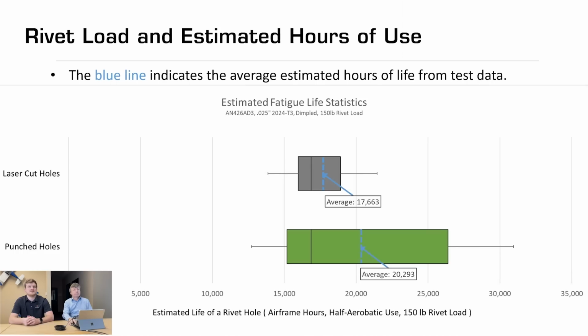So the units along the bottom here, the x-axis, are in airframe hours, but they're under a very extreme use case. Realistic flying predicts roughly 10 times higher what we would truly predict a fatigue crack onset to be for that single highly loaded hole.